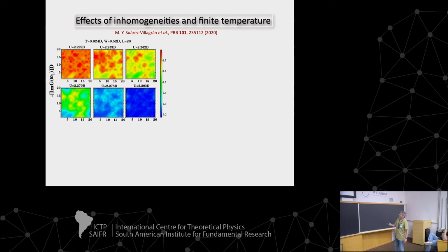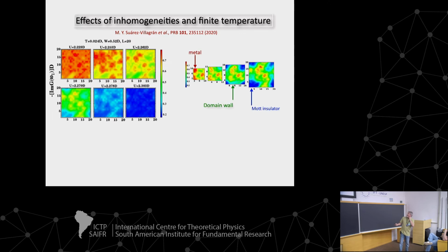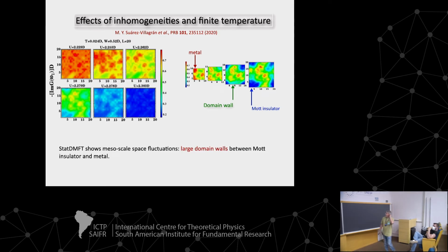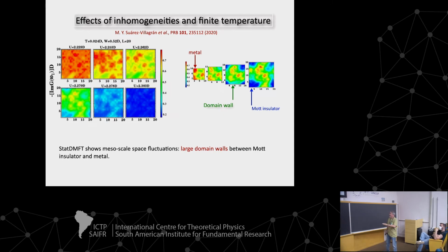You can clearly see that as you crank up U, you go from the insulator to the metal, but you have domains, you have large domains, and you have interfaces between them. Okay? So StatDMFT shows these mesoscale space fluctuations with large bubbles of insulator and metals and large domain walls between them. If you define the middle of the road here as the green color, you see that the domain walls, which are the green regions, are very large.